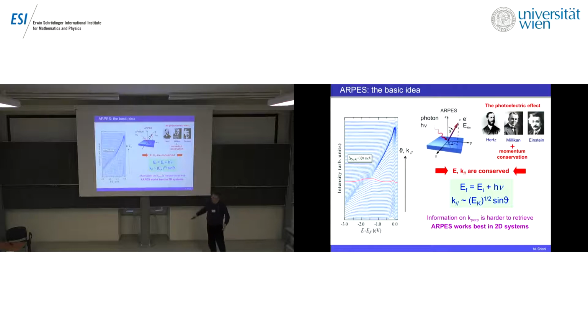Well, this is a real example. These are photoelectron spectra measured as a function of emission angle or as a function of parallel momentum. The actual system is not really important, but what is important is to see that you can really trace the dispersion of these bands and see where they cross the Fermi energy, which, by the way, is a technicality. You may ask about it, but we know exactly where the Fermi energy is in our experiment.